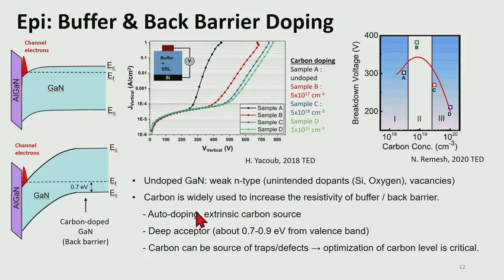But in spite of this benefit, we cannot keep increasing the carbon level in the back barrier or the buffer layer, because first, if you increase the carbon level too much, it degrades the crystal quality of the gallium nitride. And also, if the highly doped carbon layer is too close to the channel, it can cause a severe electron trapping.